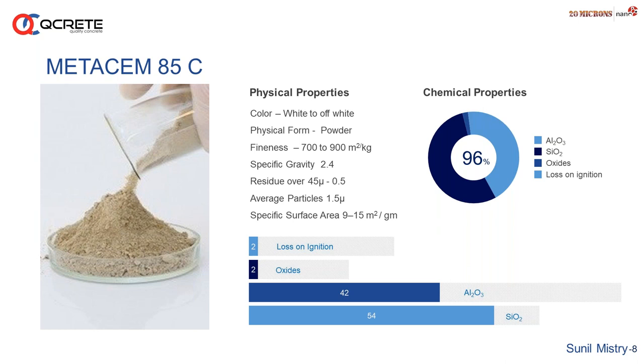It is generally available in the powder form. Liquid supply into slurry, with 50 to 60% solid content, is also possible. But metakaolin doesn't require being supplied as a slurry because it has the unique property of easy dispersion. The moment you put it into water, it disperses, not dissolves, very easily. You need not do additional stirring to disperse it. It has a fineness of 700 to 900 square meters per kg.